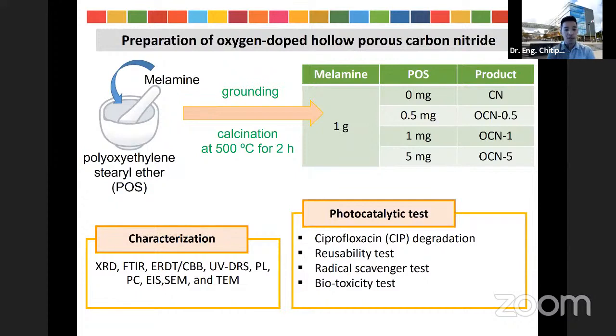So when we mix the POS with the melamine as a precursor of the graphite carbon nitride, the mixture was calcined at this condition, 500 degrees C for 2 hours, to prepare the oxygen-doped hollow porous graphite carbon nitride. Also, we vary the content of the oxygen dopant by varying the content of the POS precursor. Then we check the phase structure and optical property by these techniques, XRD, FTIR, or UV DRS spectrum. And also we apply this material for the ciprofloxacin degradation. The ciprofloxacin, or CIP, is a pharmaceutical drug, and sometimes it can be a waste when it leads to the national water reservoir.